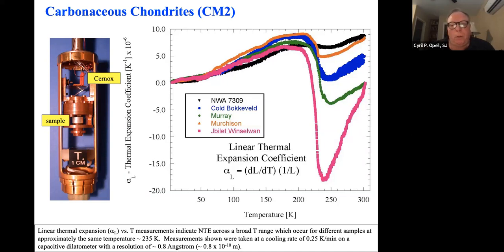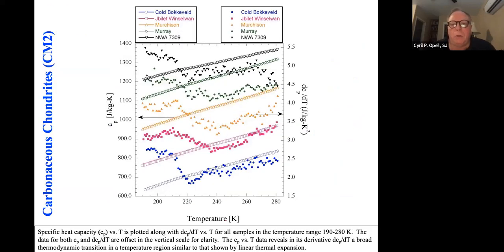But to see this phenomenon, and by the way, negative thermal expansion is very rare. There are only maybe 100 materials that have been measured that show it. And understanding what is behind the negative thermal expansion is a very important part of this paper. Now, also being a careful physicist, I was very concerned that I was seeing something that really wasn't there. And so there's a relationship between heat capacity and linear thermal expansion. And so if I could find the transition in heat capacity, and it's actually hard to find, this is probably this transition here, this bottoming out here.